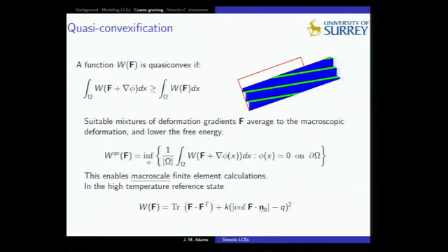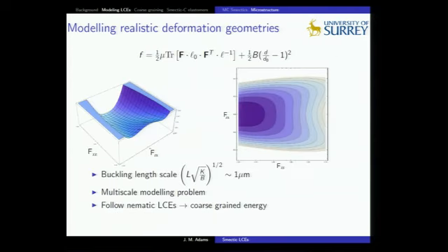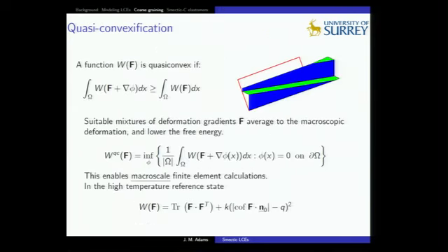We've also made an approximation that K is very large, so this cofactor F dot N norm is approximately Q, so we can write it in this slightly simplified harmonic way instead of having the cofactor in the denominator, which is what you'd have in this sort of expression. But as Randy said at the start of the week, hopefully these all reduce to the same sort of theory of Smectic, so we should be okay.